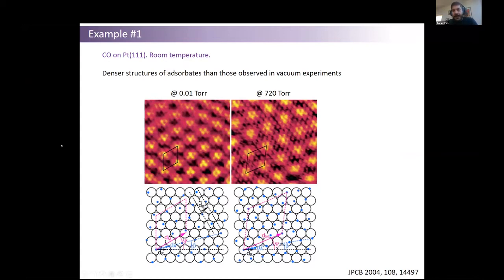But we can see already that at ambient pressures, the results are quite different from what people get in traditional surface science studies at ultra-high vacuum conditions. Now here, what you see is the STM image of the platinum 111 surface in the presence of either 0.01 torr or 720 torr of carbon monoxide. And in the image here, each bright structure corresponds to one CO molecule. You can see that there is a quite dense structure of carbon monoxide on the surface.